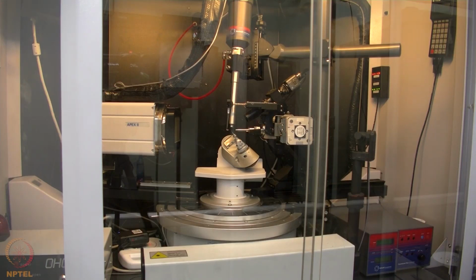So now we are going to start the recording of initial few frames, where our aim is to collect about 20 frames in one orientation and then 3 different orientations. So 3 into 20, total 60 frames will be recorded with a width of 0.3 degree, and the exposure time that we will use is 10 seconds, and the detector will be kept at 60 millimeter, that is 6 centimeter. So now I am going to start collect.